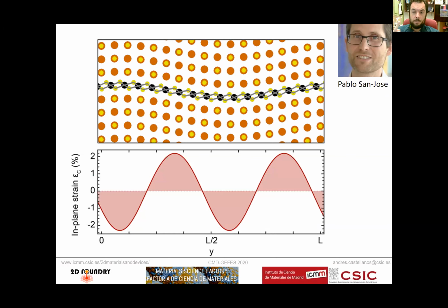But in that case, you are only applying the strain at the bottom of the layer, not at the top, right? But here it's sort of sandwiched, so I don't know, it's a competition between forces. It's similar to the other. In the other problem, you have the competition between the bending rigidity and the adhesion force. And here it's basically the same, but you have to take into account also the shearing forces. But it's very similar to the other process.